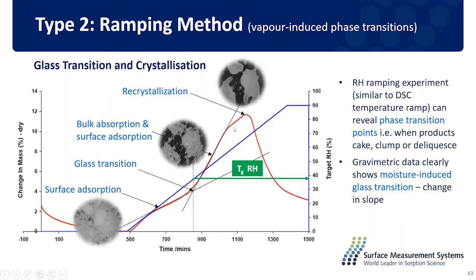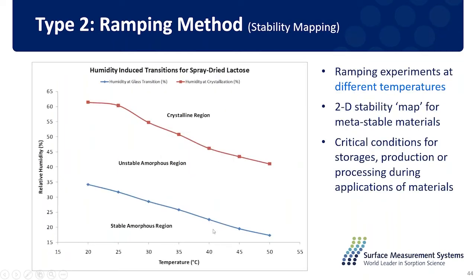When we keep increasing the humidity, the sample will also go through the crystallization step, where the mass will decrease dramatically because the crystalline state has smaller surface area and less sorption capacity. So from this simple experiment performed in one day, we can get two points. The first point is for the glass transition, and the second point is for the crystallization. These are some critical points for this sample at 25 degrees. Then we can perform the same experiment at a series of different temperatures to plot the stability between different temperature and relative humidity.